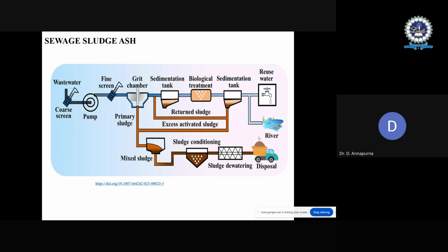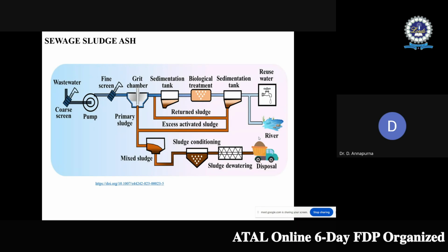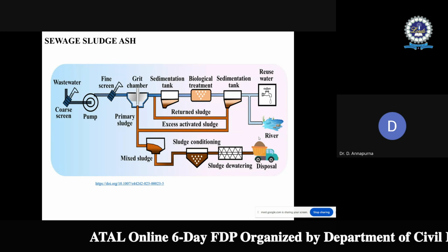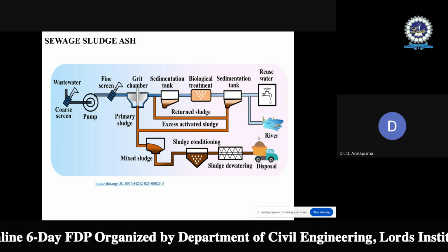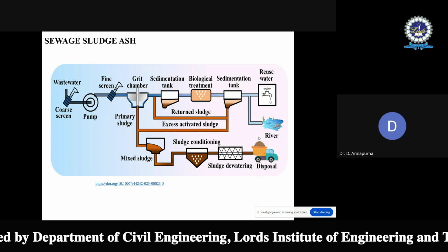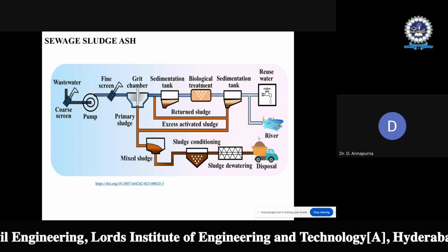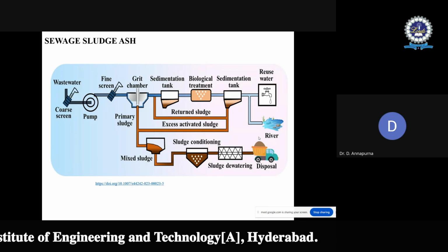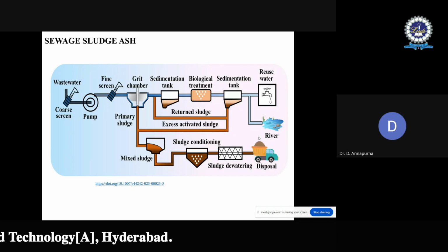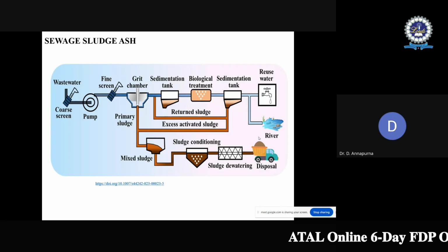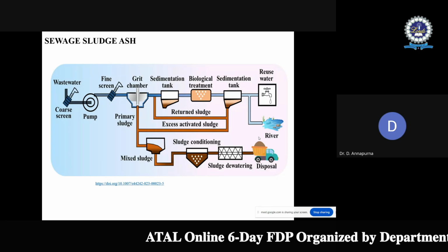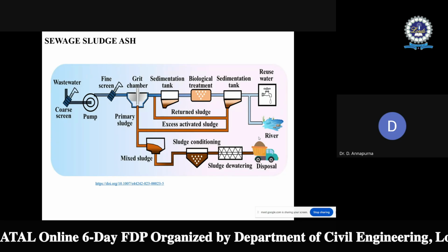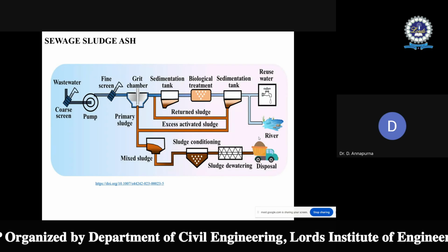This is also rich in silica and alumina. So recently in our college, sewage sludge ash was collected in Hyderabad. One waste-to-energy plant was created in Jawahar Nagar by GHMC. The waste product from that is incinerated bottom ash. That bottom ash was collected, and when XRF and XRD studies were conducted on it, it was identified that it is rich in silica and alumina.